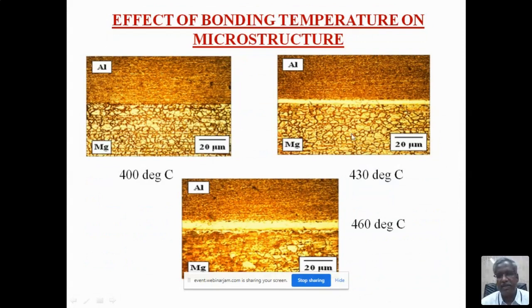This forms mainly because of atoms moving from magnesium to aluminum and aluminum to magnesium. They meet here and form a layer. That layer is called the diffusion layer. If you increase the temperature, the width of the layer increases. So with no diffusion layer, the bond is weak, and with too much diffusion layer, it is also weak, because the diffusion layer is intermetallic and brittle in nature, so the bonding strength is lower. But at the medium, the strength will be higher. So one needs to optimize at which temperature, at which pressure, and at what time you get the maximum bonding strength.